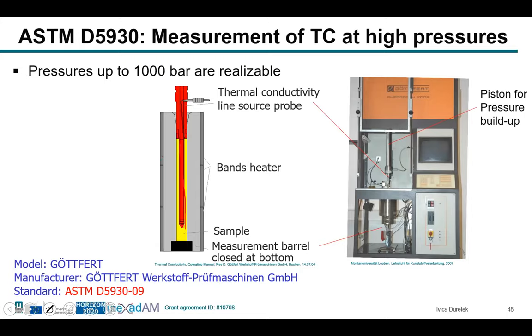We have the line source, that means the measurement sensor, which is inserted in the barrel of the high pressure capillary rheometer. The bottom side of the barrel is closed, and using the hydraulic piston, we can build up different pressures in the barrel on the material, and measure the thermal conductivity at higher pressures up to 1000 bar. This is very important for injection molding. We know that thermal conductivity increases not only with the temperature and with fillers, but also with increasing pressure.